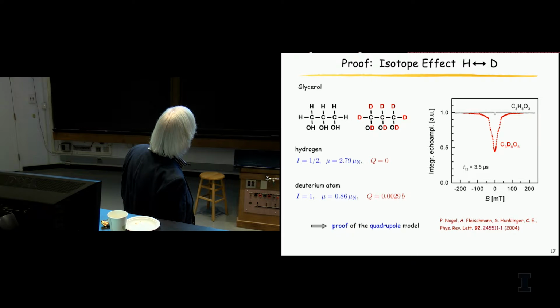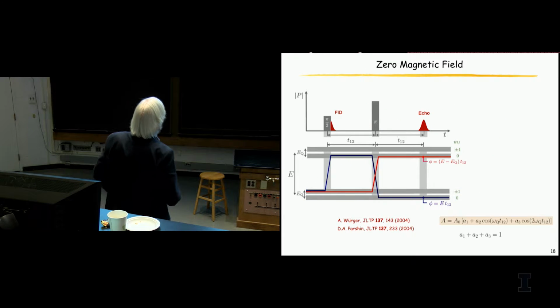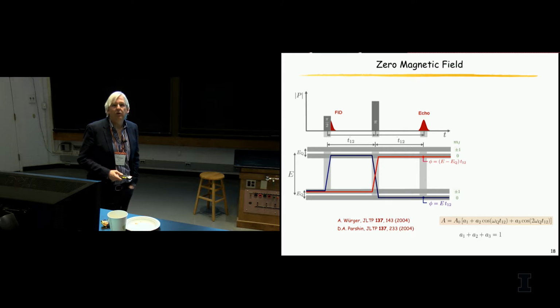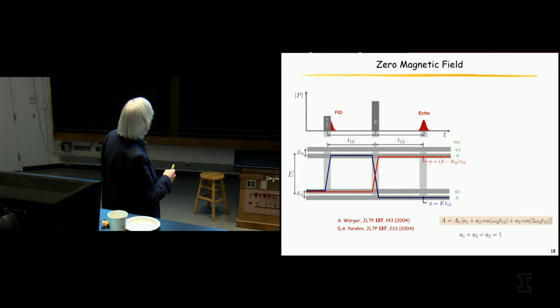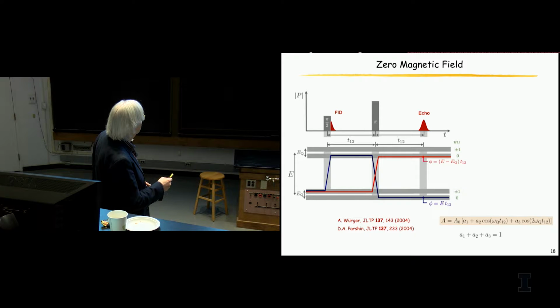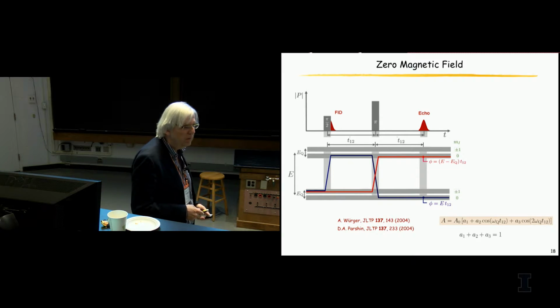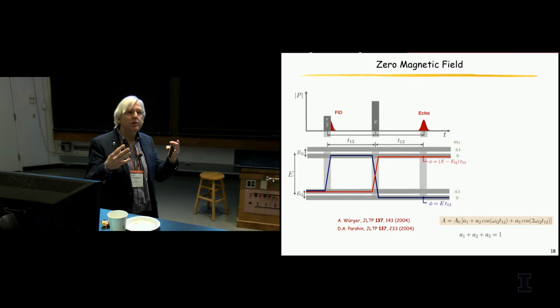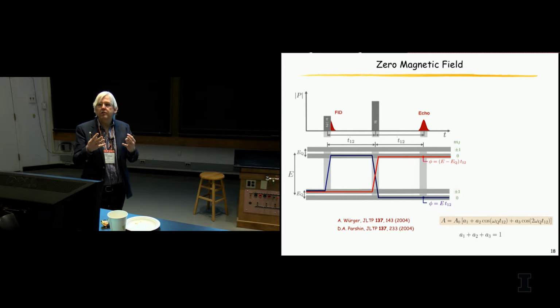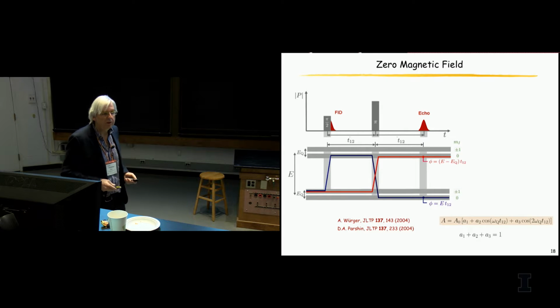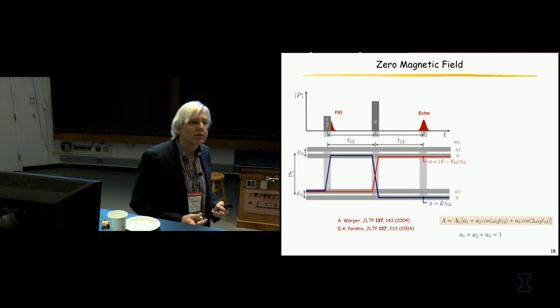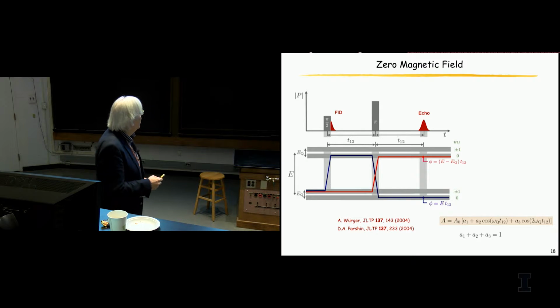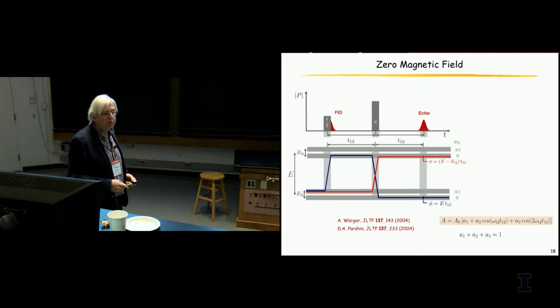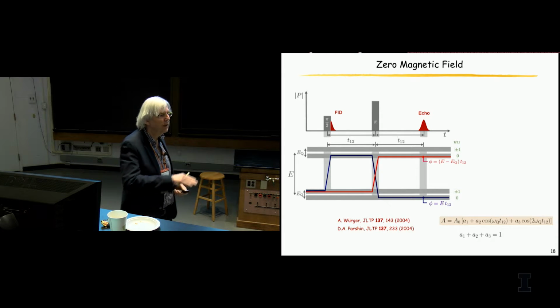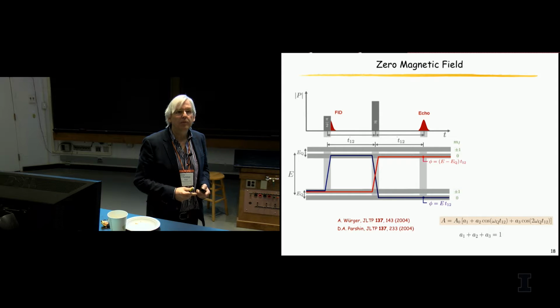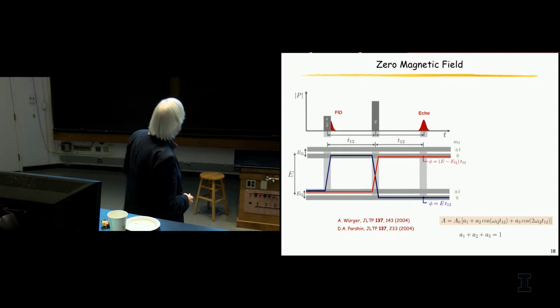Now, one can go one step further. You can look again at zero magnetic field in the echoes. In the case of deuterated glycerol, you have 4 levels, of which the one here is split by the quadrupole energy. So if you have 4 levels, and remember such an echo experiment is basically an interference experiment between those levels here, so if more than 2 levels, you get an additional phase factor. And this modulates the amplitude. So what you expect is that you get a modulation of the decay, yeah, a quantum beating. And we were looking for that.